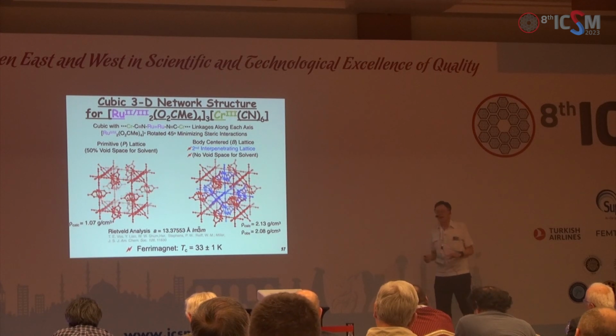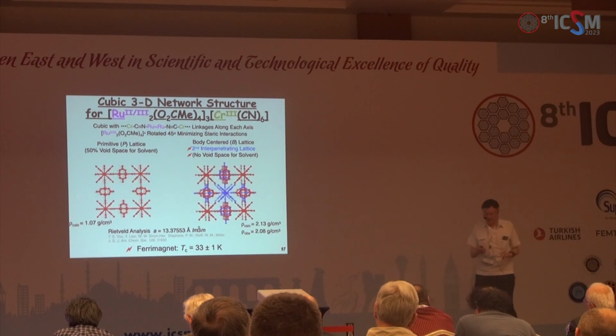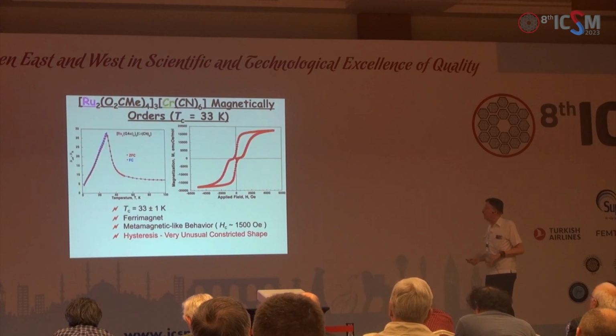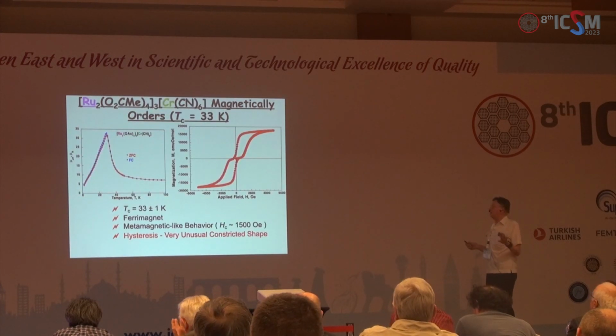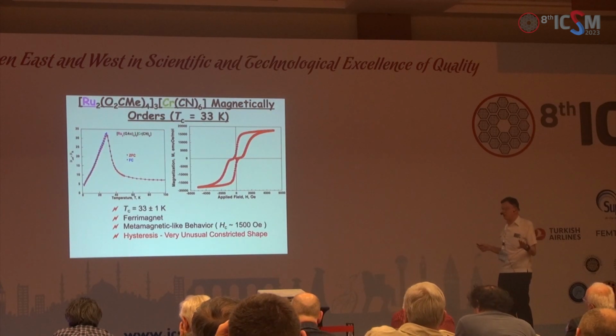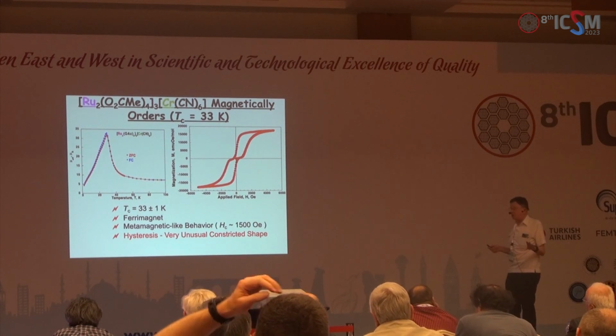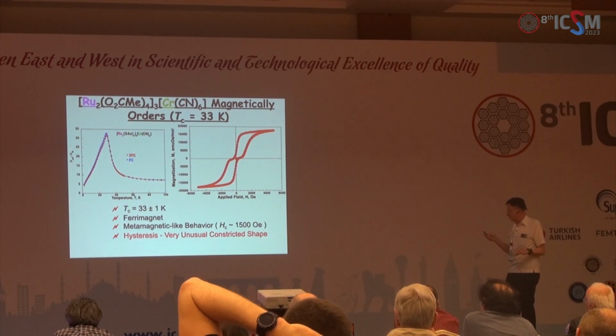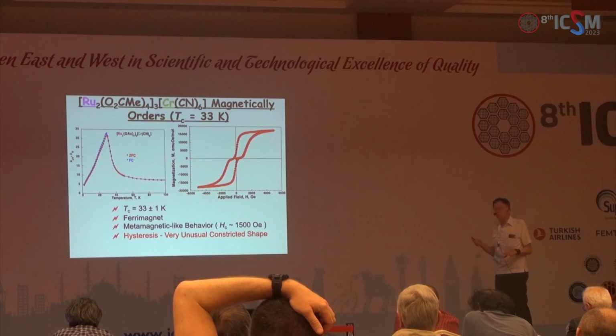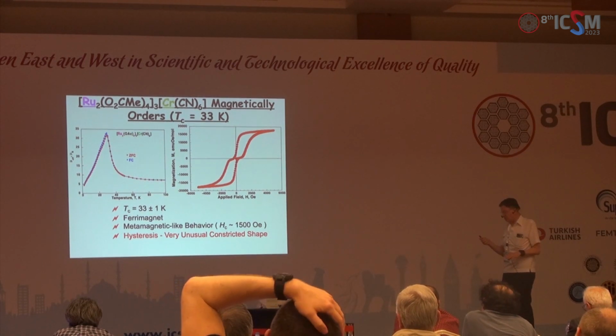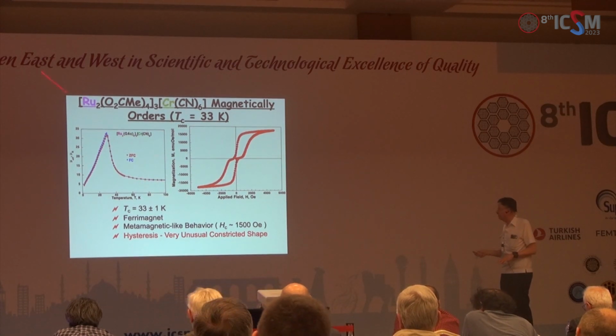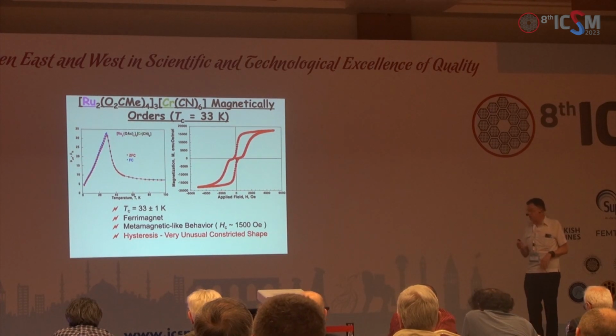And it's a ferrimagnet, an unusual ferrimagnet that orders at 33 Kelvin. I want to show you there is no bifurcation of zero-field-cooled and field-cooled data, which is unusual. The hysteresis loops—I call them 'mysteresis' loops because of the mysterious nature of these materials—have this kink in them reproducibly, a constricted shape.